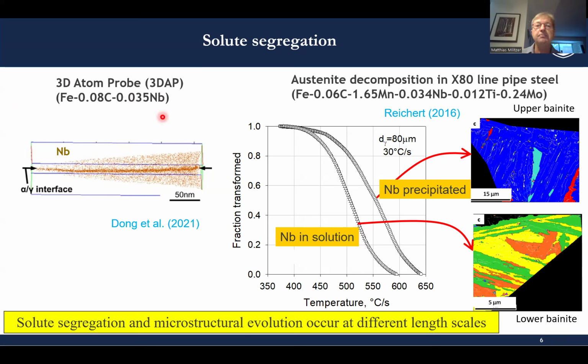0.035 weight percent niobium. If you look at steels of relevance, we look a lot at line pipe steel. Here we have an X80 line pipe chemistry that also has essentially a similar amount of niobium microalloying. And of course, there are a few other elements, so the chemistry is a little bit more complicated. We were able to conduct experimental studies with an austenite grain size of 80 micrometers, which is relevant for the weld heat affected zone, which is important for the integrity of a pipeline construction. We were able to do a preheat treatment, in one case to have niobium precipitated, in the other case most of the niobium in solution.